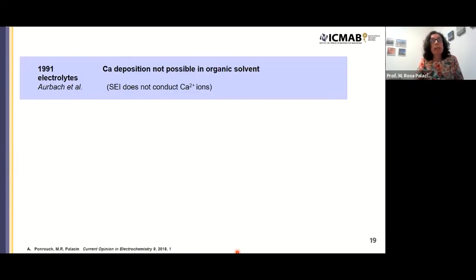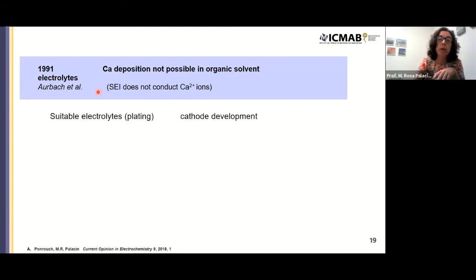But the thing is that even if we were successful, we would be able to have very good performance. The field has not been developing, mainly because, as I was mentioning, of the general thought that calcium deposition was not possible. This was again stated in a paper in 1991 by the group of Doron Aurbach, who were the pioneers in the development of the magnesium batteries. They tried to deposit calcium from organic electrolytes, and their conclusion was that it was not possible, again due to the fact that the passivation layer would never conduct calcium ions.